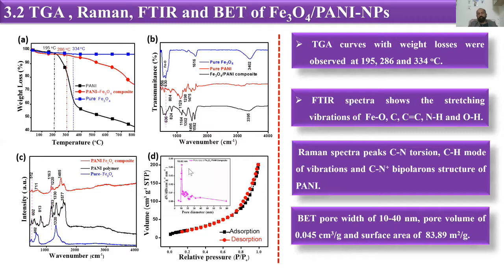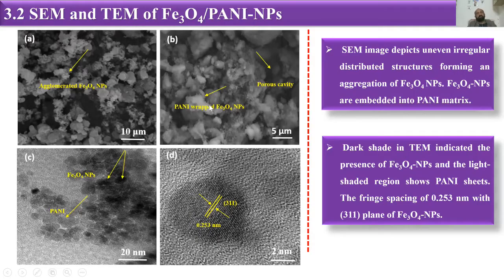We have got a BET pore size width of about 10 to 40 nanometers, a pore volume of about 0.045 cm³, and a surface area of 83.89 m²/g. Then we have done SEM and TEM of our Fe3O4 nanoparticles. Again, we have got agglomerated Fe3O4 nanoparticles, and the Pani is wrapped by Fe3O4 nanoparticles, and we have some porous cavities as well, which are very good for supercapacitor materials. And we have done HRTEM and indexed the planes of Fe3O4 nanoparticles, which reveals that our synthesis of the materials was successful.